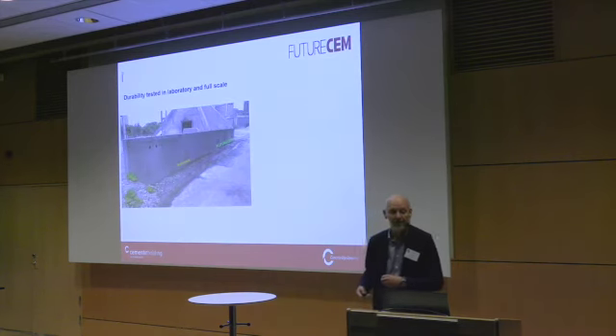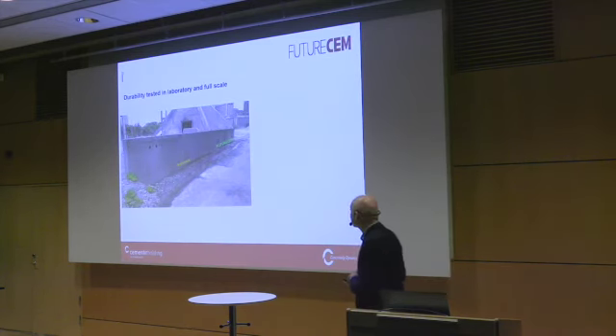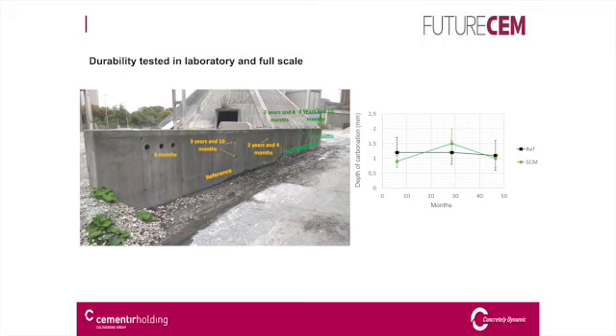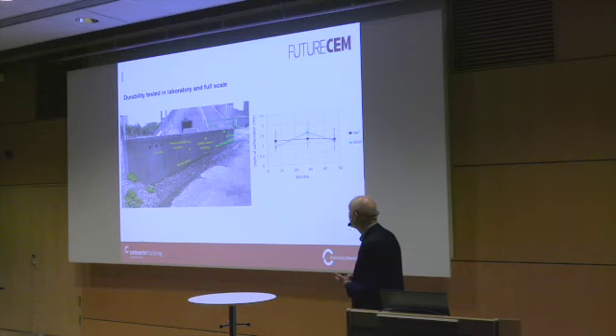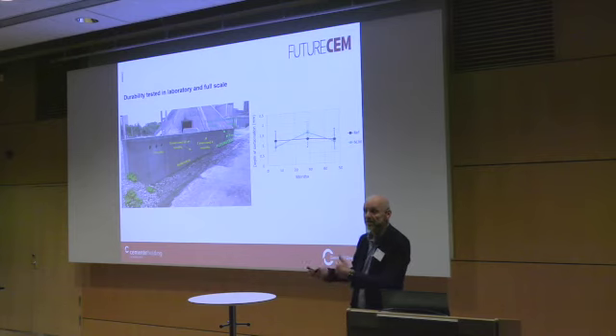And what was done here is, well, some results. This is actually the wall, which is now, I suppose, 8 years old. That was the first full-scale thing we did. Now it's full of holes, of course, because we use this for long duration testing. And this is just a picture to illustrate the durability test which was done on the new cement types, both in the laboratory and in outdoor exposures. We have exposure sites even at one of our deep sea harbors in order to document that this new cement type was a viable cement type in terms of durability.